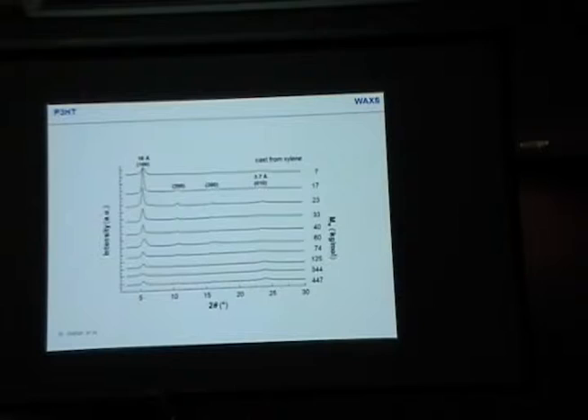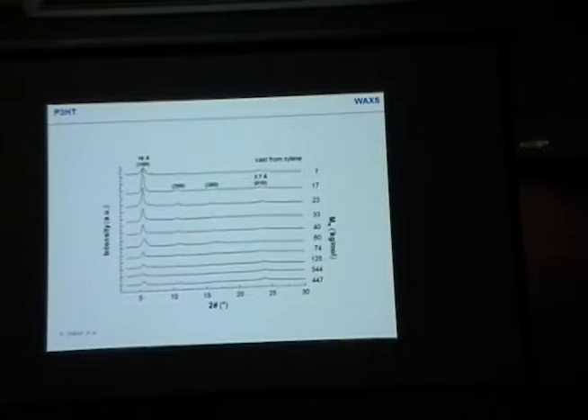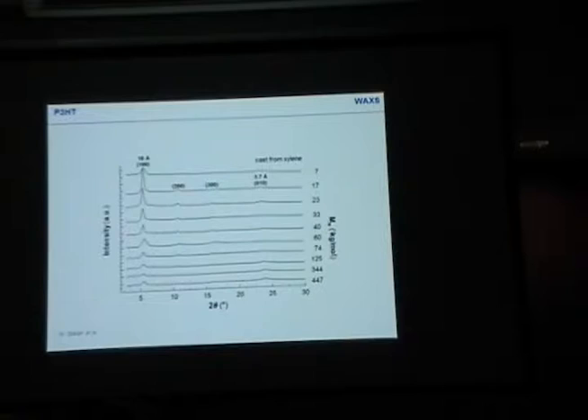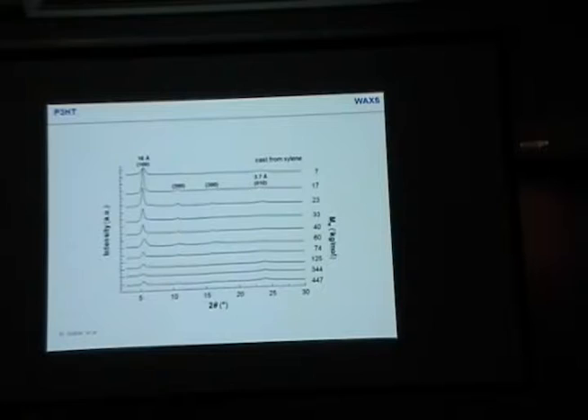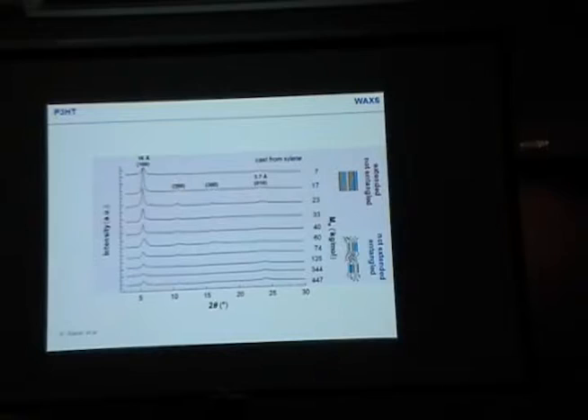One word of warning: wide-angle X-ray does not help you here. A lot of people use wide-angle X-ray, but the only thing you can really deduce from these X-ray patterns is whether we don't have different crystal structures — polymorphs. You get similar diffraction peaks. You could argue this one is more intense, a bit more narrow, but it could also be an effect of film thickness. So be very, very careful with using wide-angle X-ray to deduce anything.